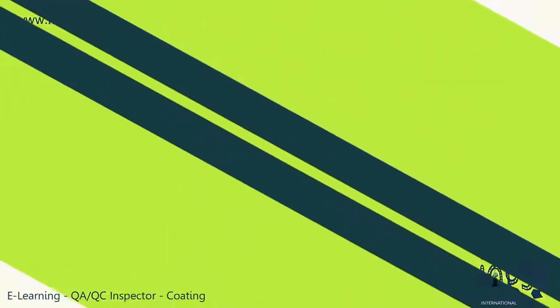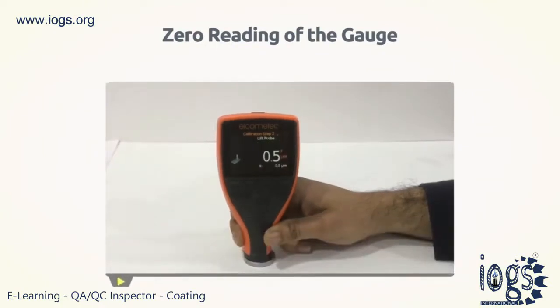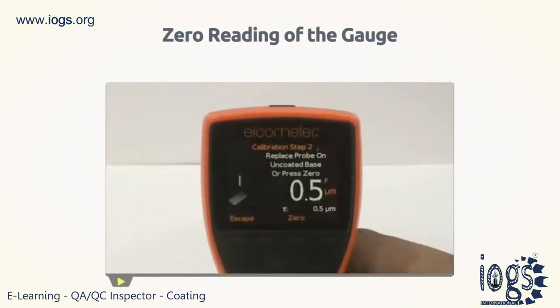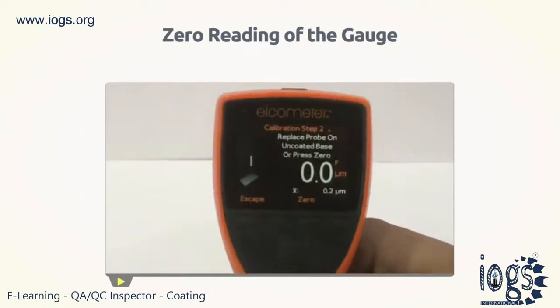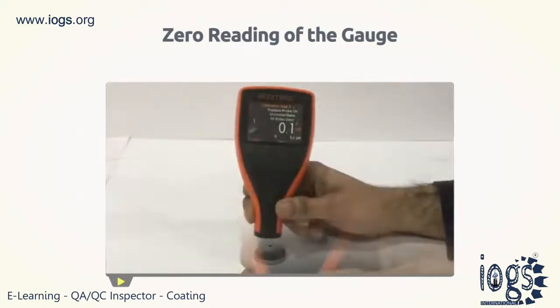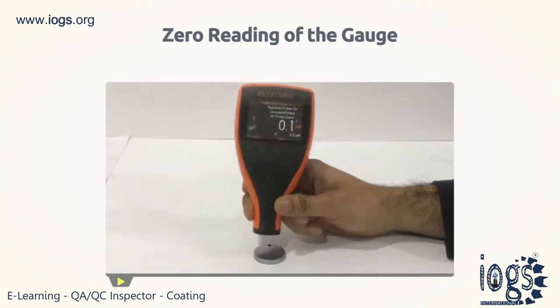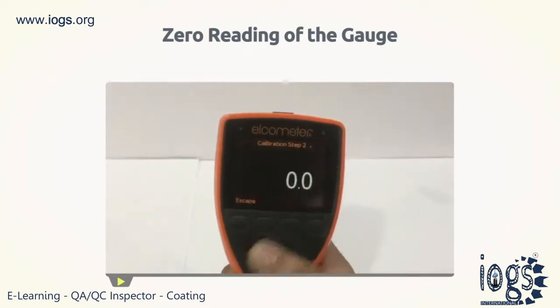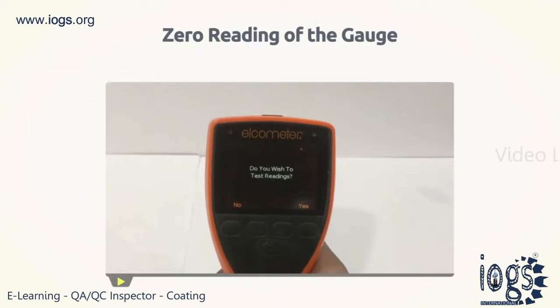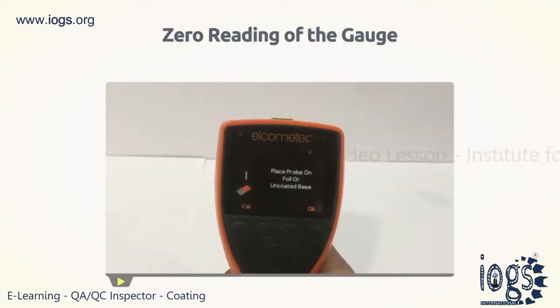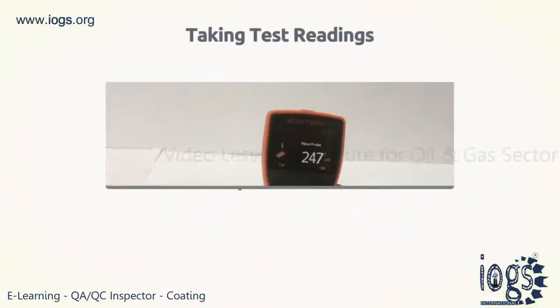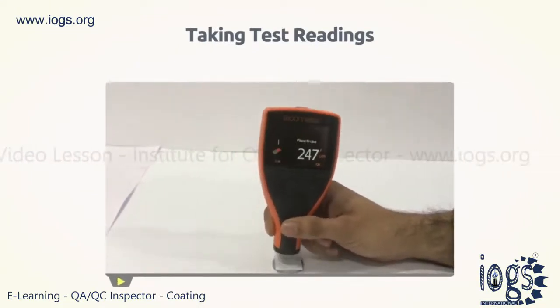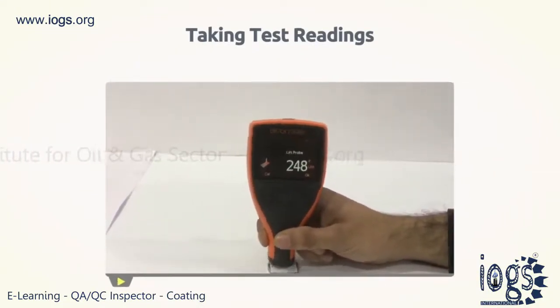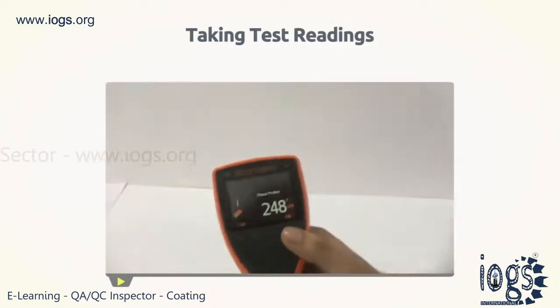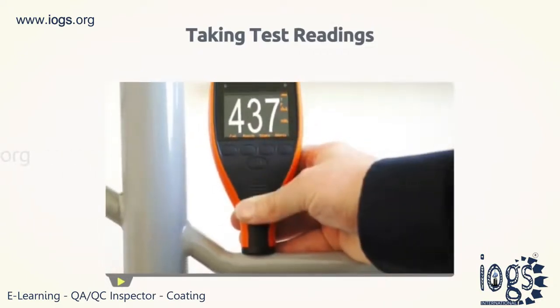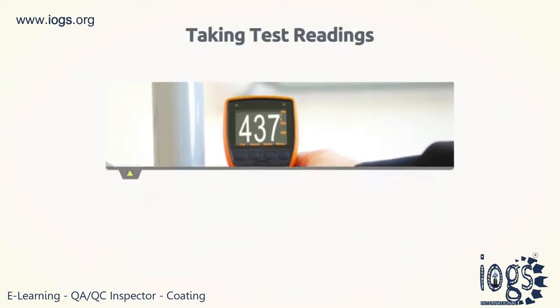The gauge will also ask the user to place the probe onto the uncoated base. To do this, place the gauge probe on the uncoated base or zero plate. This confirms the zero reading of the gauge. If the reading is not at zero, you can set it as such by pressing the Zero Soft key. You can now proceed to take a couple of test readings of the used shim over the uncoated base or zero plate. These initial readings are necessary to check the accuracy of the gauge calibration. After this, the calibration of the gauge is completed, and you can measure the DFT of a coating.